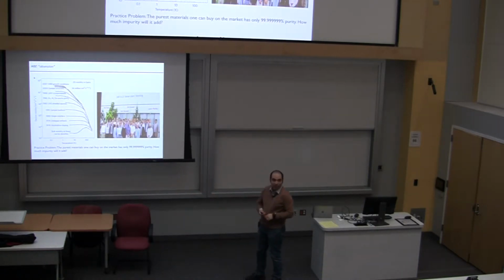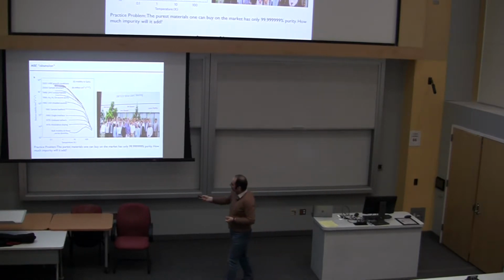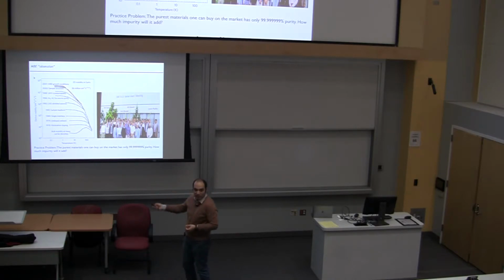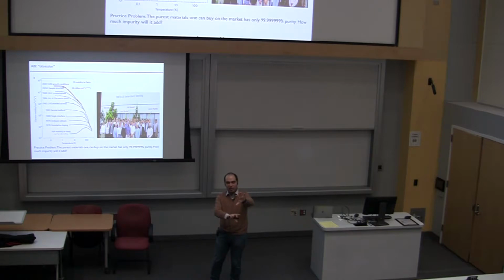So that's great. And there's this thing we call MBE obsession, and I guess this is kind of a good summary. For electron mobilities, you make a quantum well of gallium arsenide sandwiched by aluminum arsenide, and you try to measure the mobility. At room temperature, it's all below 10,000. Best materials, worst materials, room temperature doesn't matter. It's dominated by other scattering mechanisms. But as you see, when you go to low temperature, where we usually use these materials, at the beginning, like pre-1978, it is all bulk, very low mobility.